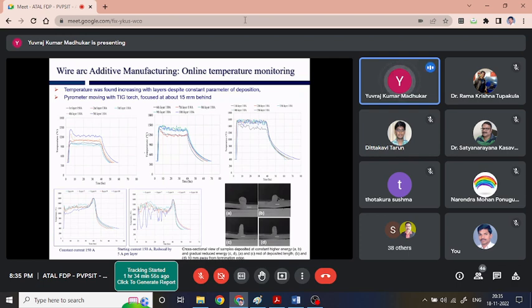So this is some initial experiment that we have conducted. Here it is basically a wall deposition process. The first layer of deposition was at 150, the second layer at 130, and from the third layer onwards we stick to 110. But still, if you look over here at the first layer of deposition, this is the temperature. The temperature was close to nearly 1000 degrees centigrade. However, in case of the fifth layer of deposition, though the input energy is reduced, the peak temperature is increased to close to nearly 1300 degrees centigrade. And as we further deposit layers on the same input parameter, we could see the peak temperature increasing to the order of nearly 1550 to 1600 degrees centigrade.